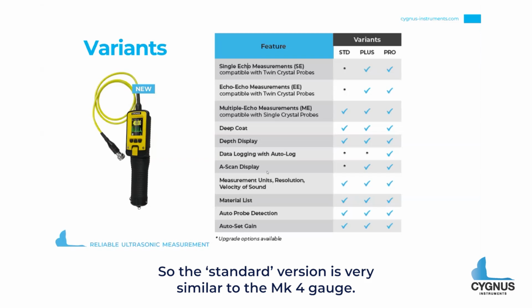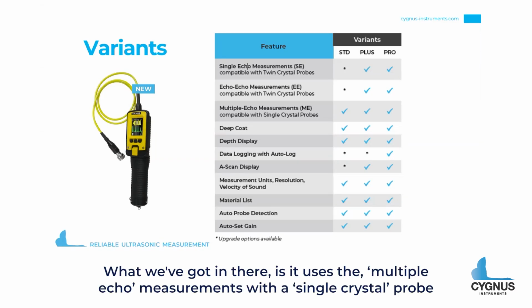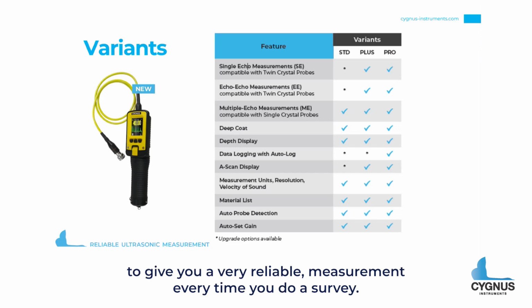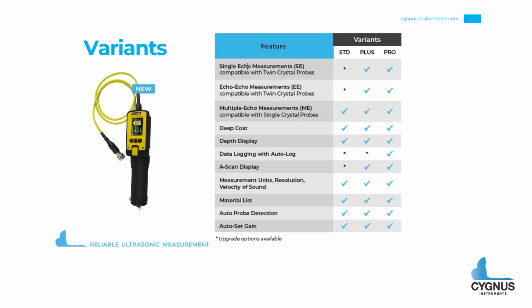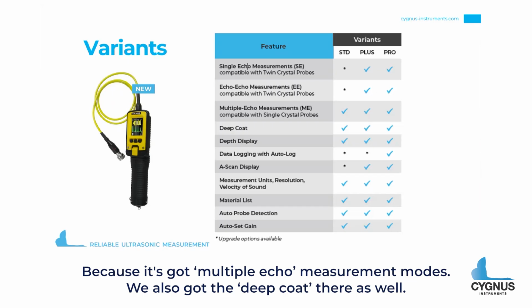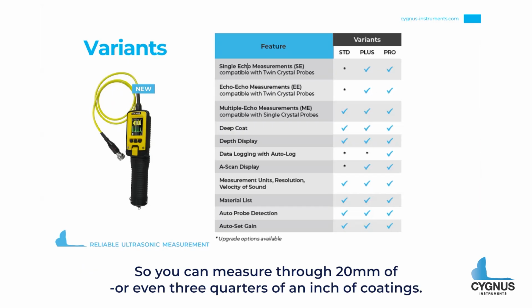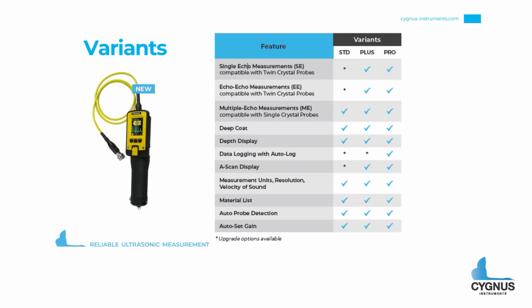So the standard version is very similar to the Mark IV gauge. What we've got in there is it uses the multiple echo measurements with a single crystal probe to give you a very reliable measurement every time you do a survey. Because it's got multiple echo measurement modes, we also got the deep coat there as well, so you can measure through 20 millimeters, or even about 3/4 of an inch, of coatings.